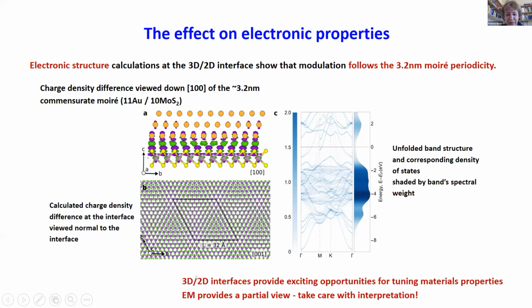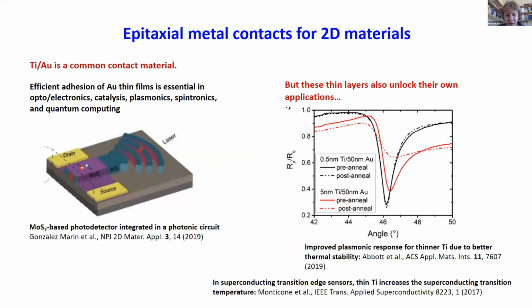So 3D, 2D interfaces are exciting and you can control them, but you have to be a little cautious about analyzing the results from a TEM observation. So let's move along from gold to some other materials, and Ti/Au is a very common contact material for conventional electronics. So how well does this work for the 2D materials? In other words, can we make nice Ti/Au layers on a 2D material?